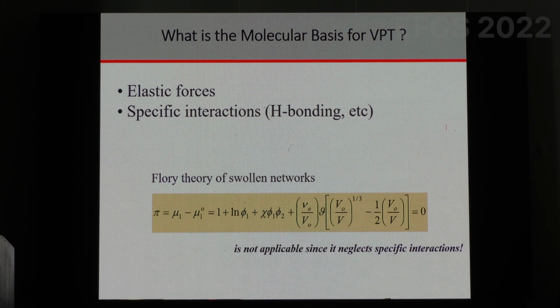There's an elastic force in the rubber band. A very similar elastic force exists in these polymers because of the cross-links. So that's the elastic force. So one must account for these elastic forces. And the other is the specific interactions. And particularly since we are dealing with hydrophilic polymers, you can expect a lot of hydrogen bonding between water and the polymer. So, if you're trying to understand the molecular basis of these volume phase transitions in these hydrophilic polymers, you must at least have a model or a theory that accounts for both of these things, the elastic forces and the specific intermolecular interactions.